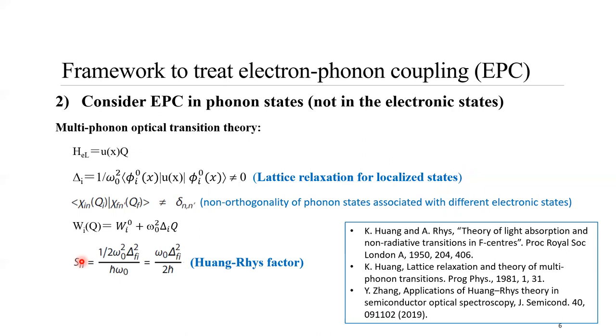The other extreme to deal with the coupling is to consider only the electron-phonon coupling in the phonon states. If we take a linear coupling approximation, we calculate this matrix element. As I already mentioned, for the bulk states this is going to be zero. However, if the electronic states are localized states, then they can be non-zero. And because of this, the atomic configurations would be different between, say, the initial state and final states. Then the phonon states are not orthogonal to each other. This effect causes a shift in the electronic state. Also, the electron-phonon coupling strength can be measured by the so-called Huang-Rhys factor, which can be calculated from this matrix element.